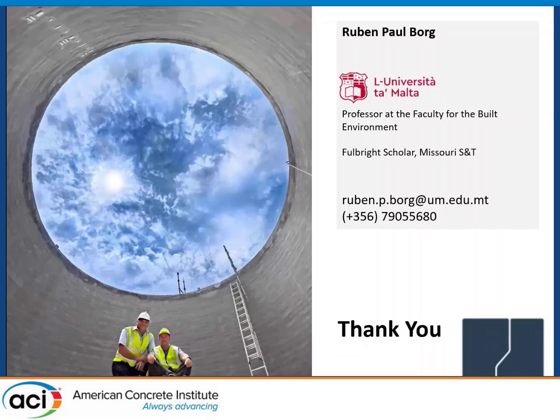So we repaired. We had to reinstate about half of the tank with new reinforcement, which was integrated then in the older structure, and we performed electrochemical chloride extraction and realkalization of the remaining structure, and then we replicated the concrete and modulus to reinstate the missing parts, but we retained as much of the original as possible. Once it was reintegrated as the original structure, we did not fill it because we weren't confident enough to do that. So we use the textile solution to have an extra reassurance, and it was over-designed, I have to say, to ensure that it can take the stresses as if the reinforced structure is not there.